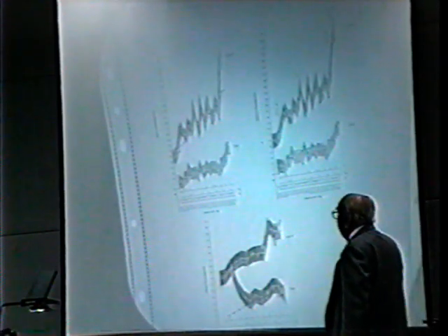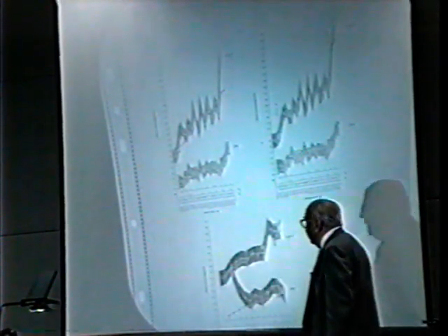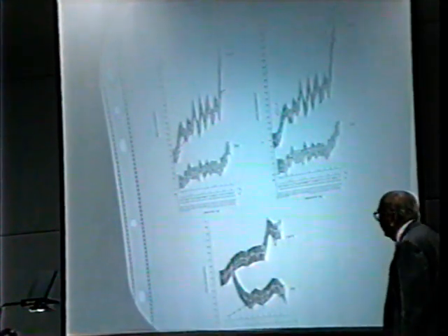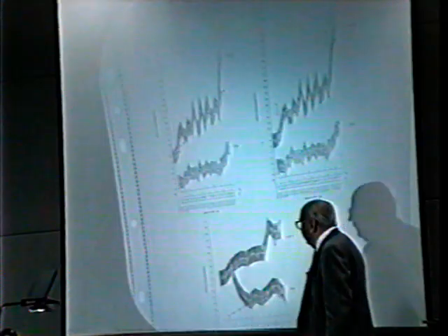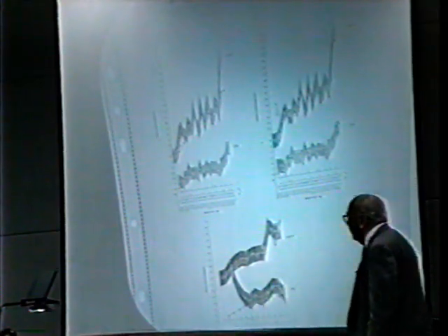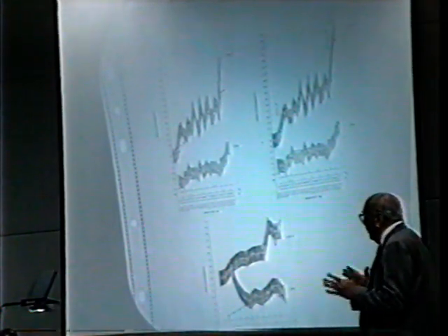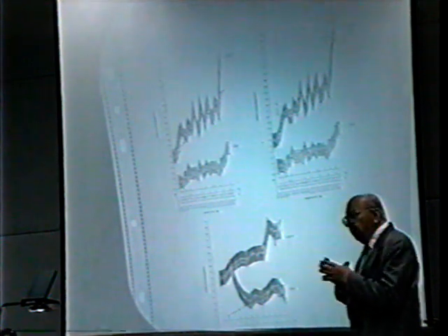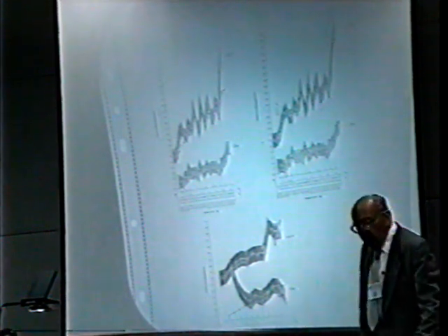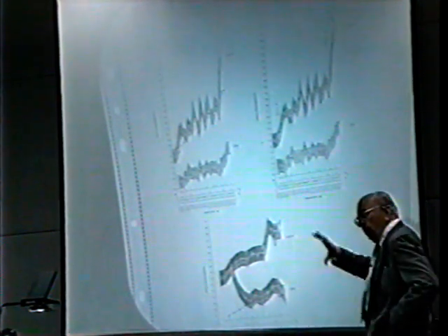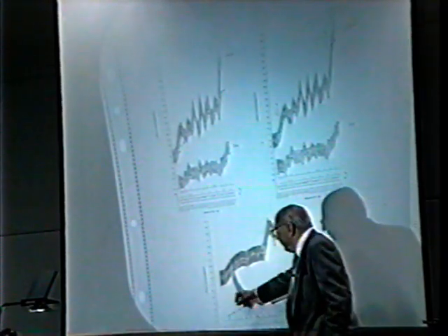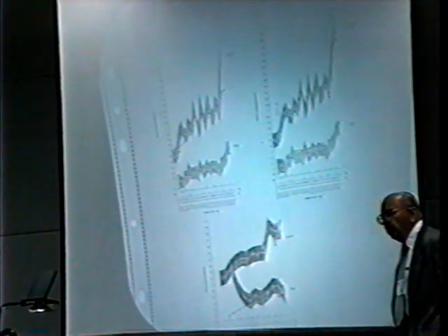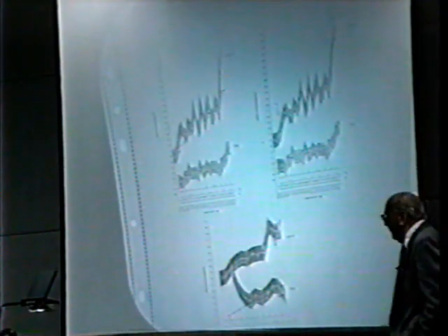Now, in this slide, you have another example. This is a tritium evolution found in the gas phase immediately during the co-deposition experiment, where the electrode surface looked like the one having the large number of globules. Here, the rate of production is much higher, several orders of magnitude. It's about 10 to the 8th.